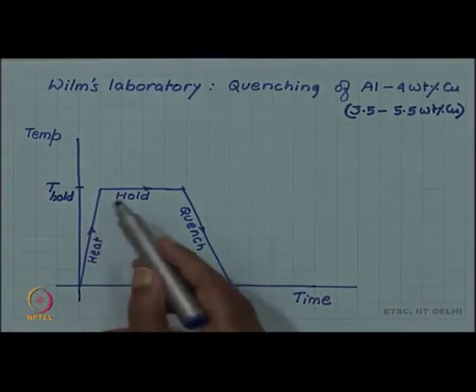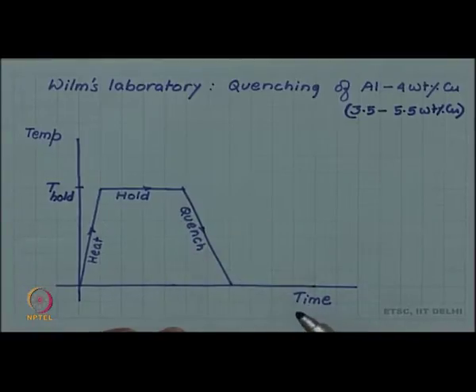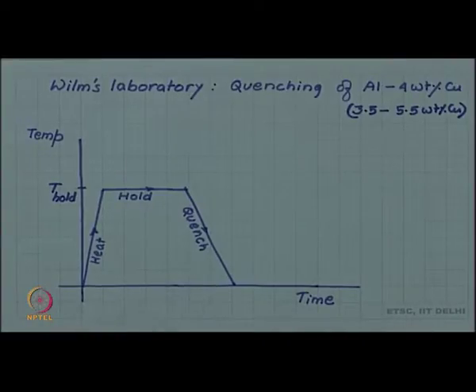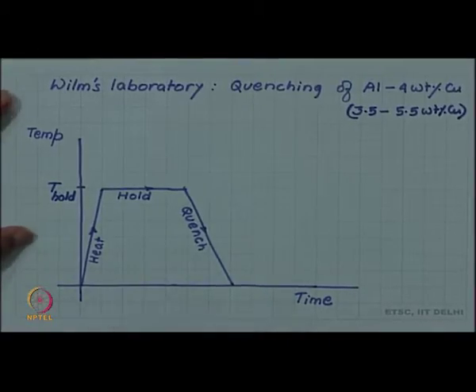He heated the sample, held it for a sufficiently long time and quenched it, but hardness did not increase. In fact, in some cases it depressingly decreased. The hardness after quench was even less than the initial hardness he started with. So the process was not being successful. But he thought about it, and he was a determined scientist.